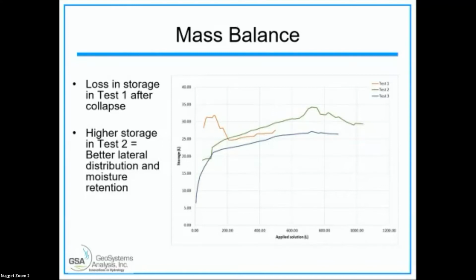So between these tests, even though we used a much longer time to ramp up, what we saw is that the slow ramp up actually had more storage. So that tells us that the solution distribution within the ore is much better. So it's moved out, and there's more mass of solution. So there's more contact of the raffinate with the ore. Next slide. So what's our conceptual model here?